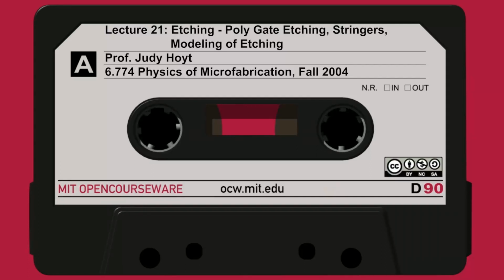Here's an example of an intentional production of a stringer. We have a substrate. We put one film on. It could be polysilicon that we have now patterned with a very sharp step. We put a second film on where we adjust the thickness of the second film to be just the right thickness, so that after I've done a purely vertical or purely anisotropic etch, when I'm done, I have a sidewall spacer forming. So this material is left behind. The nice thing about it is it's self-aligned, so I didn't have to put another mask down and do photolithography to pattern this. All you have to do is have a step in your film number 1. You put another film down, you clear the whole thing with a vertical etch, and bingo, right on the sidewall, self-aligned to it, is a spacer layer.